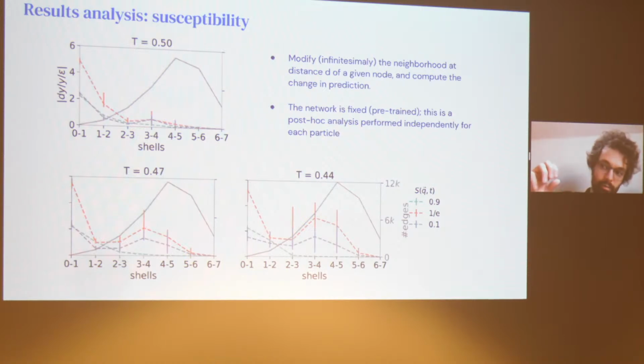If you look at how much the prediction is modified as a function of where you do the modification, the x-axis here is between which shells you are increasing these distances. On the leftmost plot, you're just increasing the distance to your immediate nearest neighbor, and then as you go to the right, you're increasing the distance between the third and fourth or other neighbors. Of course, there are more of these neighbors, so there's a bit of competition between the numbers and the distance. What this showed is that the effect is the most pronounced around the third or fourth shells. This was a good indication that the network was propagating this information from further away in the graph.